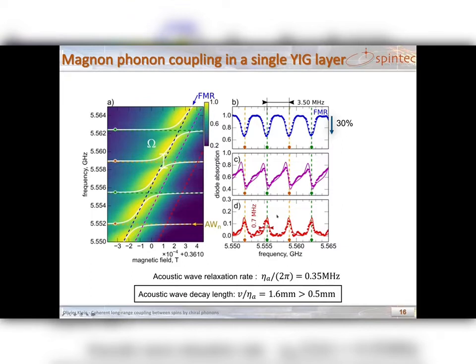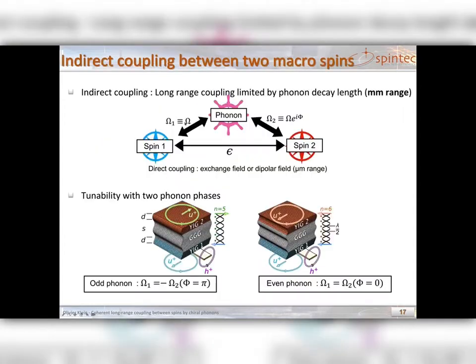And because this peak is exactly the acoustic character, we can extract from the line width of this peak the acoustic phonon decay length, which is about 1.6 millimeter decay distance, which is much bigger than the sample thickness. So now we want to establish an indirect coupling between two distant macro spins using the circularly polarized acoustic phonon. If you want to make a direct coupling between them, they should be very close or nearby, because the exchange or dipolar field have a very short decay. But for phonon-mediated coupling, it is limited by the decay length, which is in the millimeter range.